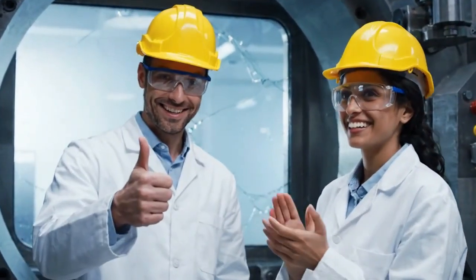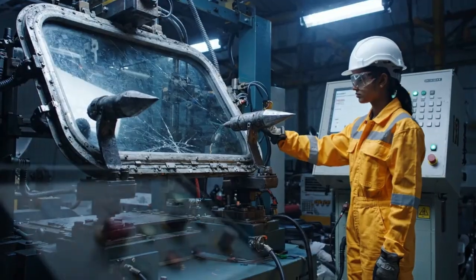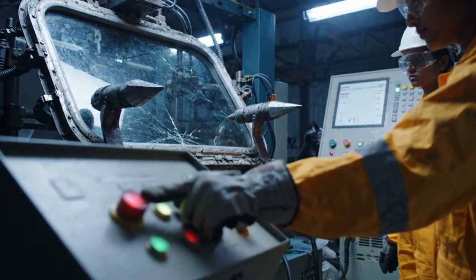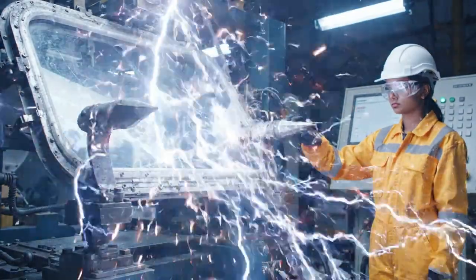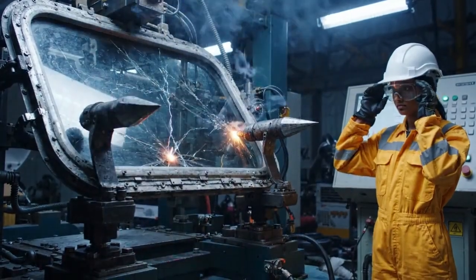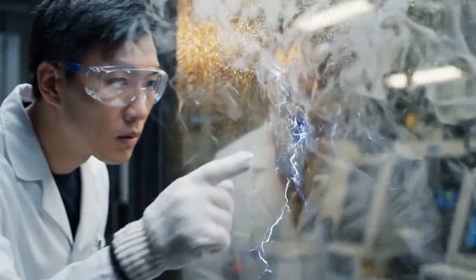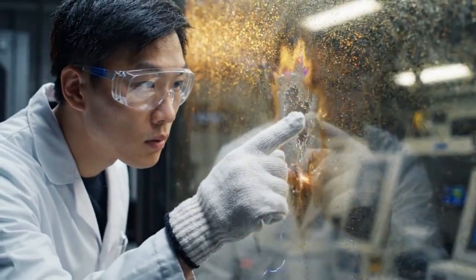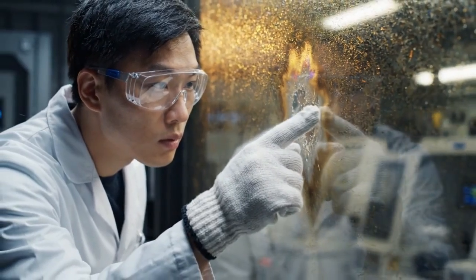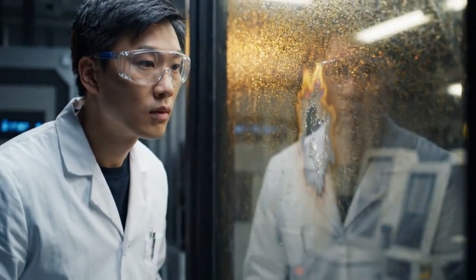But the test is far from over. Lightning strikes aircraft approximately 7,000 times per year. Each window must survive 200,000 volts, enough to light a small city for a day. The gold layer, the invisible shield, has done its job. The lightning passed through, but the window survived.